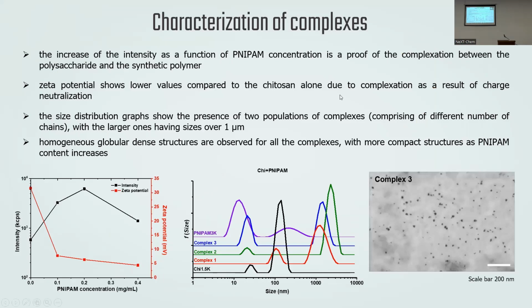So for the characterization in solution, we used dynamic light scattering and electrophoretic light scattering. In the first figure, we can observe the scattering intensity as a function of the PNIPAM concentration. And we can see the increase of the intensity as a function of PNIPAM concentration. That is a proof of the complexation between the polysaccharide and the synthetic polymer. Also, we investigated the zeta potential as a function of PNIPAM concentration, and the values are lower compared to the chitosan alone, which is due to the complexation as a result of charge neutralization.